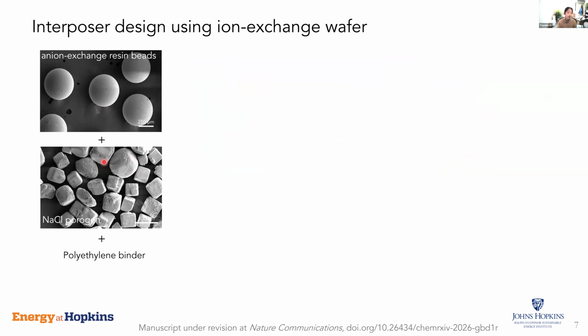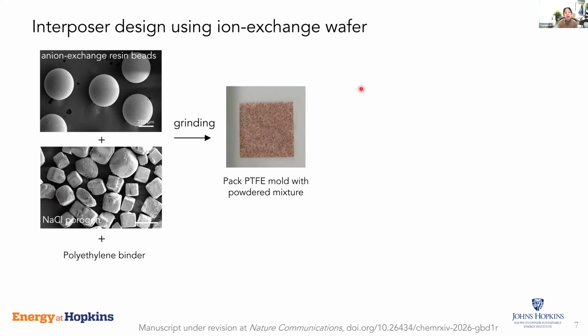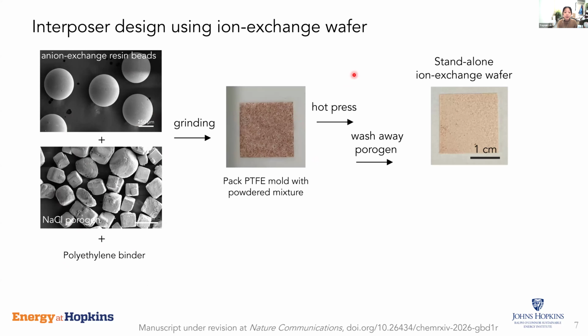You can see this kind of cubic shaped sodium chloride. And then we mix these two together, we grind them, and then we add some sort of polymeric binder to kind of glue them together. After grinding, we can put them into a plastic mold to shape them in whatever size and thickness we want, followed by thermal treatment, a quick hot press.